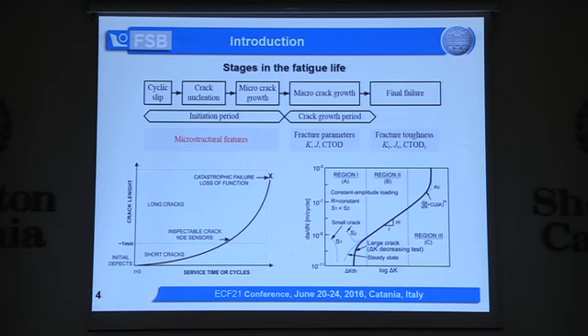So, when we don't have residual stresses, this is a typical crack growth behavior. At first we have slow and small crack growth rates, and then crack propagation speeds up. So when we consider a simple plate without residual stresses, we have this situation here, but residual stresses may change this. And with our model, we are here in the Paris region, and we will apply some power law models like Elber and Schijve.